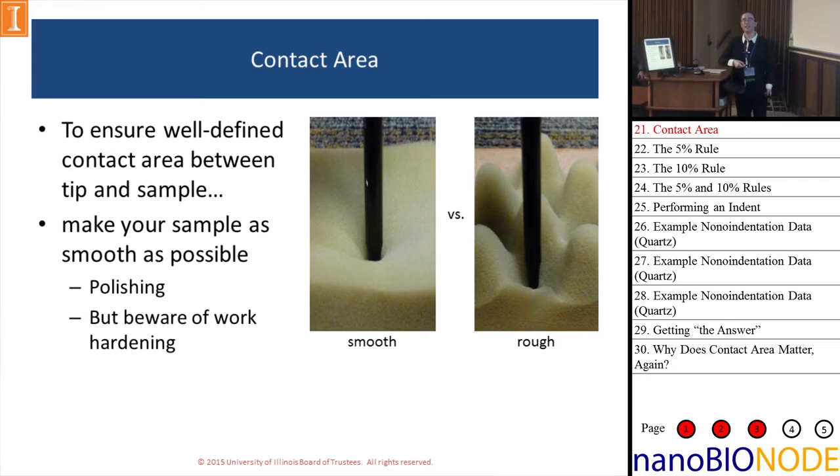So in order to smooth out your samples, many people will polish them. But you can't polish a hydrogel, so sometimes this doesn't work for people's samples. And also, polishing tends to leave little bits of the polishing material behind, like Rick's really cool way of getting the silicon carbide thing. That would be an artifact in this case that you wouldn't want.